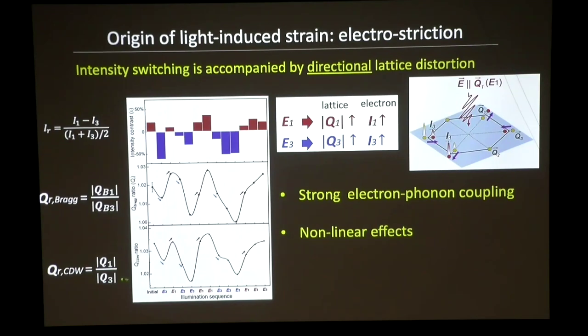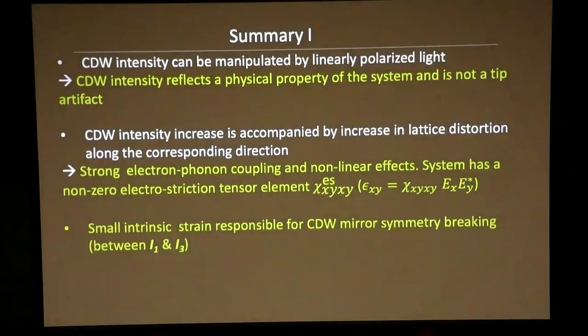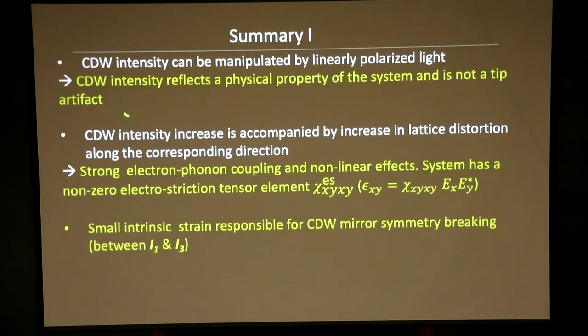In fact, there's a direct correlation. Every time the charge density wave gets stronger, the Bragg peak in that direction moves outwards, which means that the atoms are actually getting closer. So a stronger charge density wave is associated with a larger lattice distortion. That's what this light tells you. Okay, so what have we learned by shining light? We've learned that the CDW intensity can be manipulated by light, okay. It tells you that the charge density wave intensity as measured by the Fourier transform is a physical property of the system, and it actually has physical meaning, and it's not an artifact of the tip or something else.